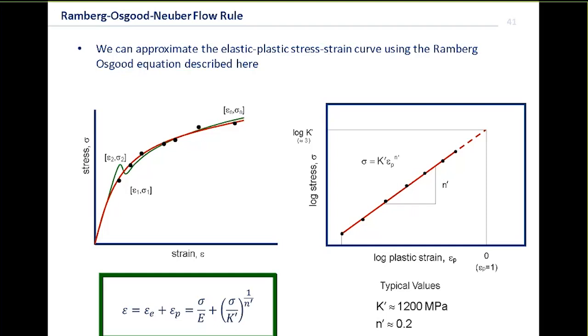So the way that we find the parameters for this Ramberg-Osgood is simple. The first thing we do is we look at the low stresses and we fit the elastic line through that. We find the modulus of elasticity E. Then when we get to those higher stresses where there's plasticity involved, we subtract the elastic part and we plot on log paper the remaining parts. And if we fit a straight line through those, we can then find out the K prime and N prime. So all we're doing again is fitting a straight line in log space.